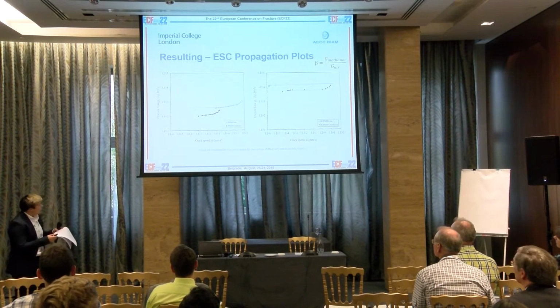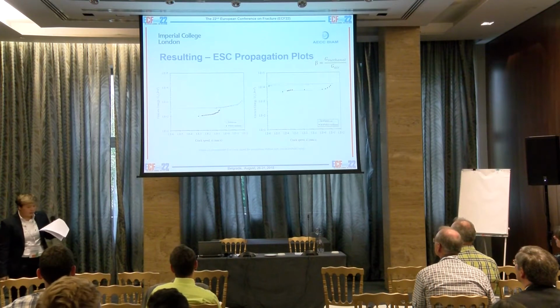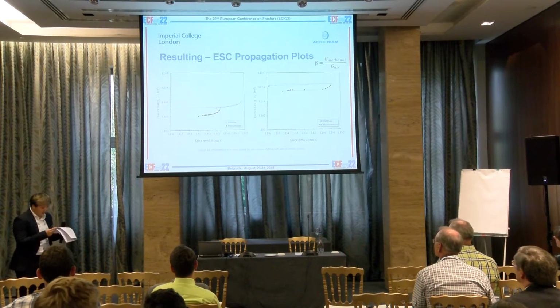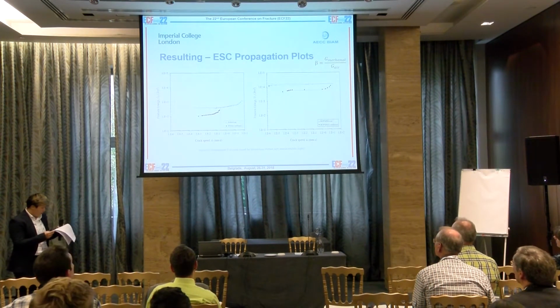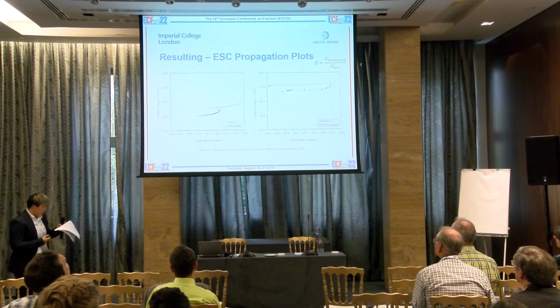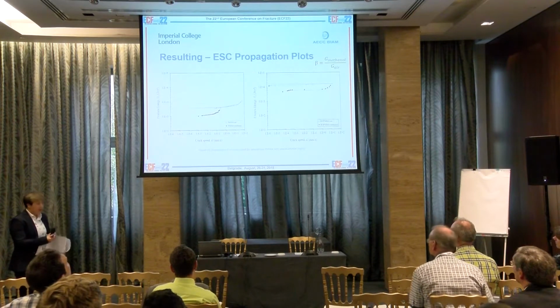The plasticization factor, beta, which is the ratio between the average G methanol and G air for both polymers, can be found. So the smaller the value, the greater the environmental effect it has on the polymer.